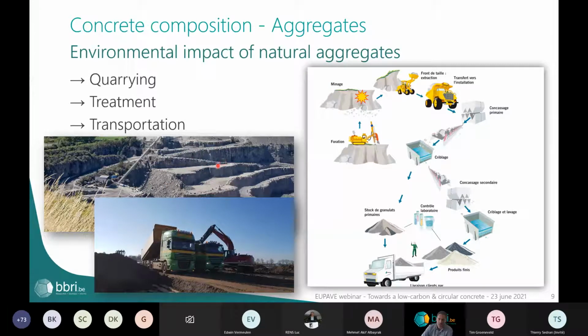You can also get the aggregates from riverbeds and from the sea, but those from the riverbeds are being more and more depleted. So there we cannot use the quantities that we need for concrete anymore. And the aggregates coming from the sea, the coarse aggregates, cannot be used as such in concrete. They are not of high enough quality. The form is not good for concrete. So we're mainly looking at the quarries for the coarse aggregates.